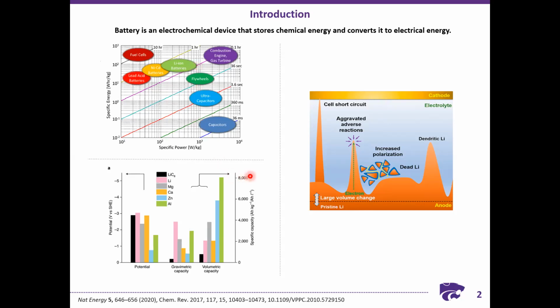Basically, the holy grail of battery anodes is the lithium metal because of its very high gravimetric capacity, as you can see from this plot. Currently, the graphite anodes have a very low gravimetric capacity, while the lithium metals have a very high gravimetric capacity. Also, in this paper, they have characterized batteries with zinc metal as anodes. Lithium metal anodes exhibit high gravimetric capacity, while zinc metal anodes provide a huge volumetric capacity of around 6,000 ampere-hours per liter, since zinc is a divalent cation.